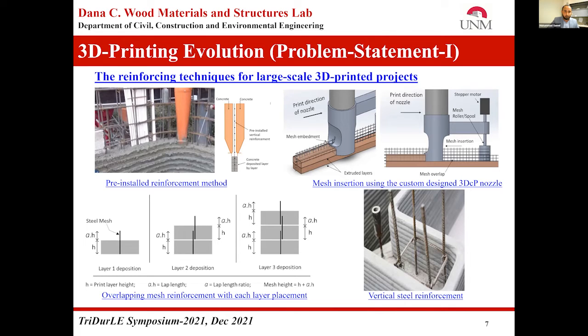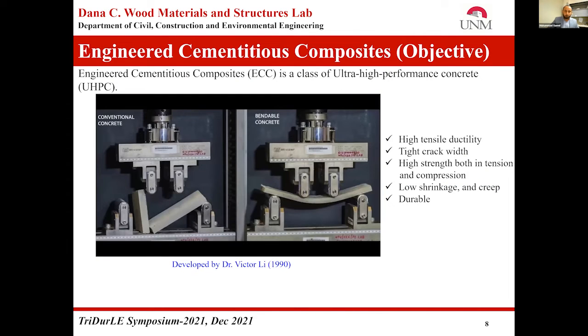And we claim that we don't need labor force in 3D printed concrete. So to address the issue of reinforcement, engineered cementitious composite, which is a class of ultra high performance concrete, could be an alternative to minimize the required reinforcing bars to some extent, because this ECC has potential of providing high tensile ductility, tight crack width, and it has high strength both in tension and compression, and durability is also very good.